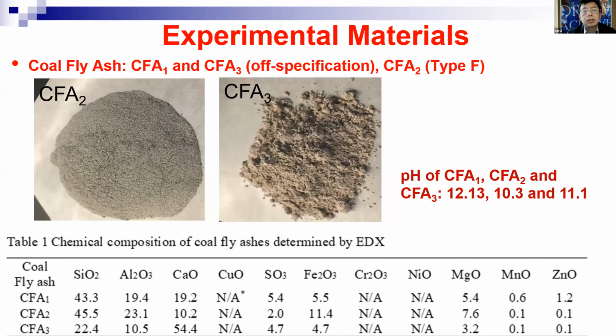Basically, type F has a calcium oxide content of about 10%. It's low, so it's difficult to use for self-cementation. You have to add an additional calcium solution for cementation purposes. The other two fly ashes are off-specification. So basically, they're not exactly class C or class F, a little bit off.